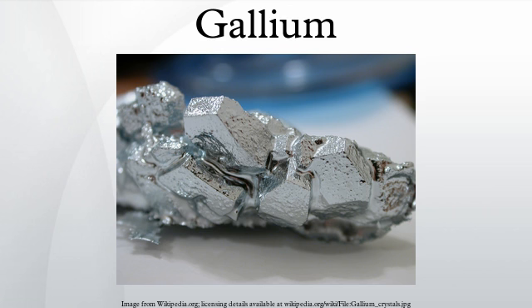In 1986, the production was estimated at 40 tons. In 2007 the production of gallium was 184 tons, with less than 100 tons from mining and the rest from scrap recycling. By 2012 world production of gallium was an estimated 273 metric tons. In January 2013, the market price of gallium lay at $580 USD per kg, while by autumn that year, it had dropped to around $280 USD per kg, or just under $9 USD per ounce.